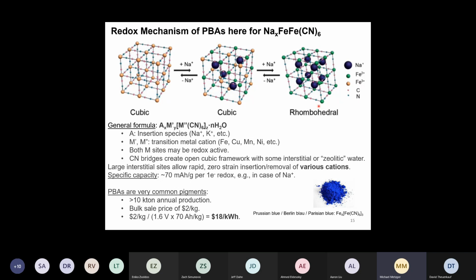So you can do that, but it goes along with a change of the crystal structure. And we will see actually at the very end that this is currently a challenge for these materials. Of course, it would be very nice because you get twice the capacity, but these materials don't cycle well anymore if you do that. In the same case, but I would say this is not very well understood yet. If you fill it up to this stage with divalent ions, you run into the same problem.